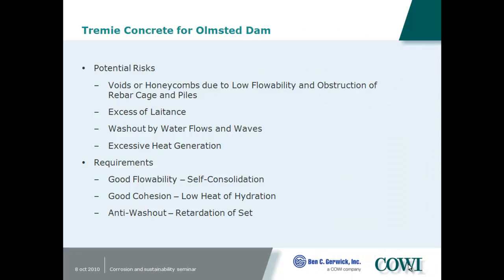So of course, there are risks of honeycombs. There are concerns about laitance. Laitance is when a little bit of the fresh concrete mixes with the water, and there's a little bit of surface to the concrete, so the concrete's better down below the surface. There's concern about washout, and particularly heat generation here, so we use a large quantity of blast furnace slag for a large concrete placement. So we had good flowability, was self-consolidating, low heat, and self-retarding.